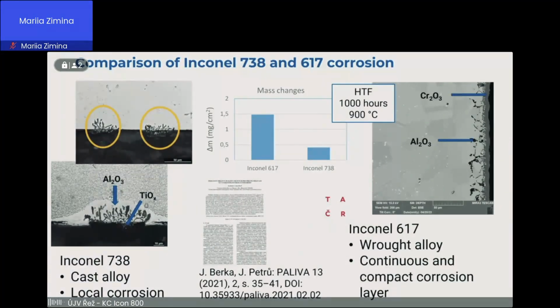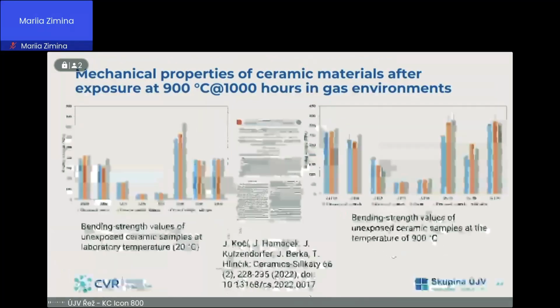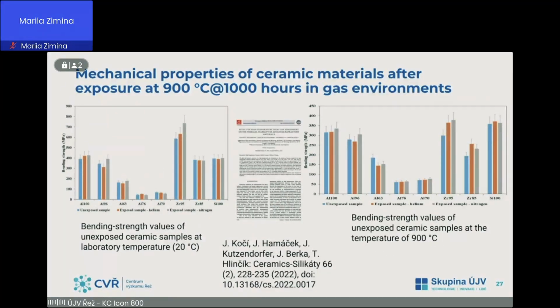But we will see in the next results, because Inconel 738 was also included in a new experimental program. But last but not least, new data about the bending strength changes of new ceramic materials exposed in hot helium, and for comparison also in hot nitrogen, was obtained and also published. Also in this case, the differences were relatively negligible.